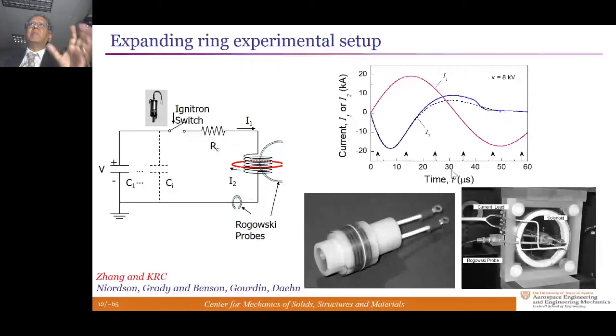Over the years, there have been a number of different ways of instrumenting this. The most common one is to measure the currents flowing in the coil and in the specimen. These are the measured values of the current. They are on the order of tens of kiloamperes, so they're very large and potentially dangerous currents. But you measure them, you know the driving force, and so you can calculate what the response should be. And most commonly, they picked up pieces of the broken specimen and identified from that some average measure of strain.